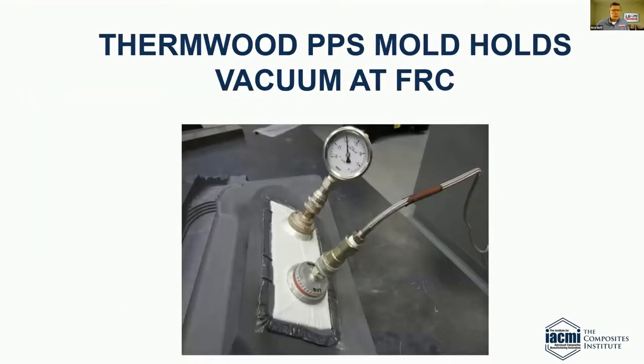The first material that we were most excited about in the tooling world was PPS. And PPS is a high temperature material. It's semi-crystalline, and you could load it with up to 50% carbon fiber, meaning that it has a very low CTE. But one of the problems was that most printers could not print it to the point where it was dense enough that it would hold a vacuum. It needed to be sealed with a secondary operation. The THERMWOOD LSAM was the first one that could actually print this material without coatings that could hold a vacuum.